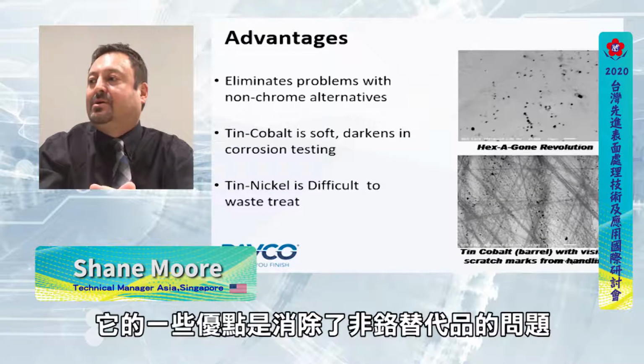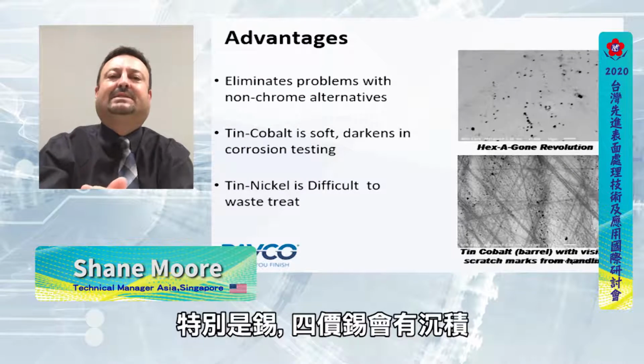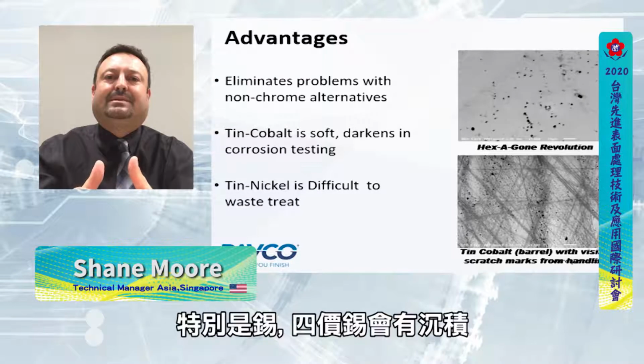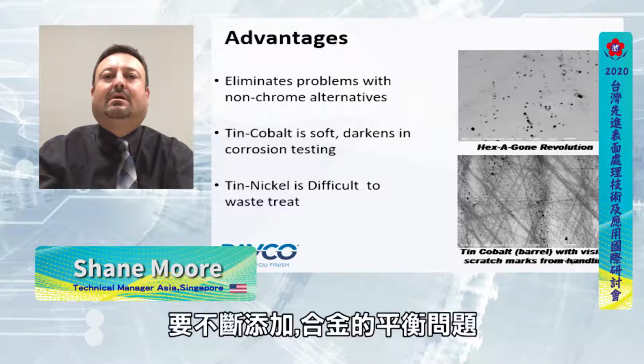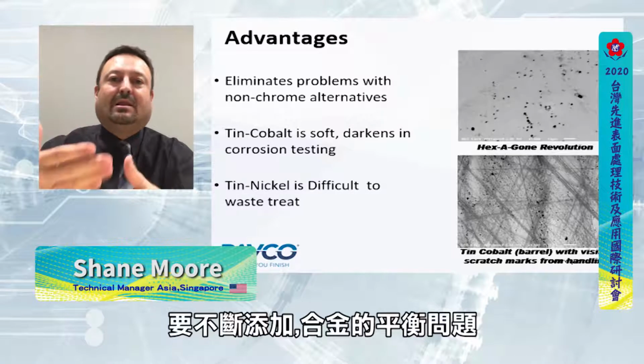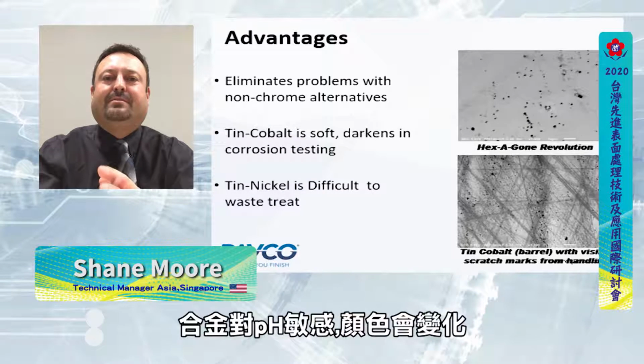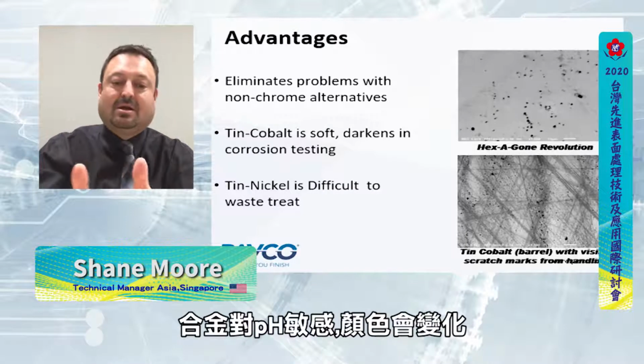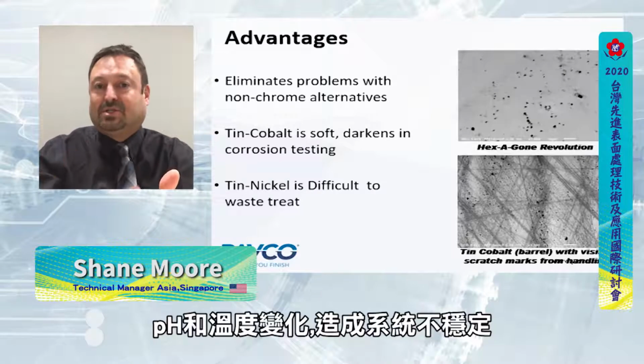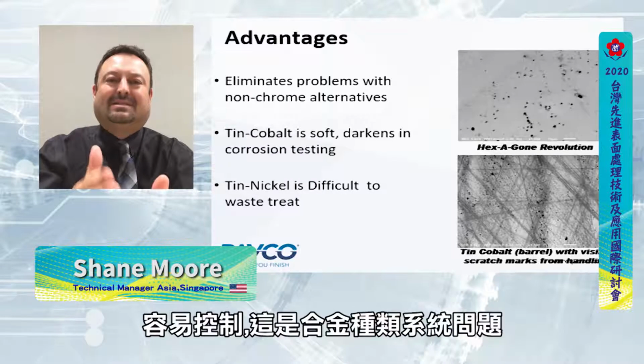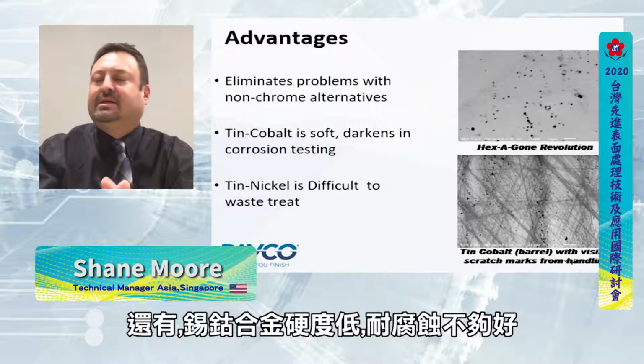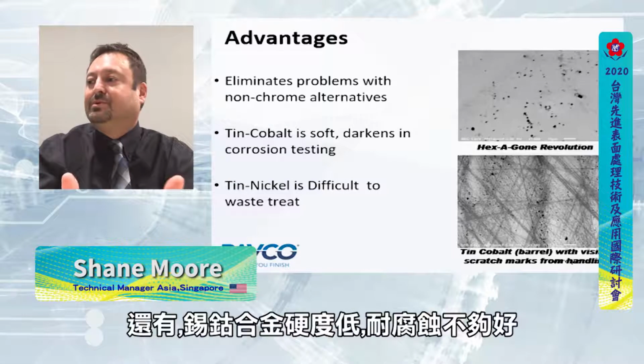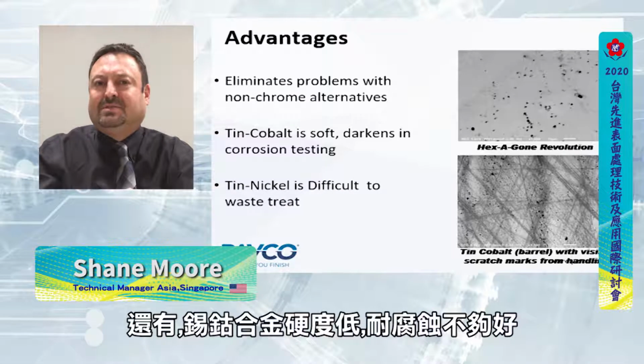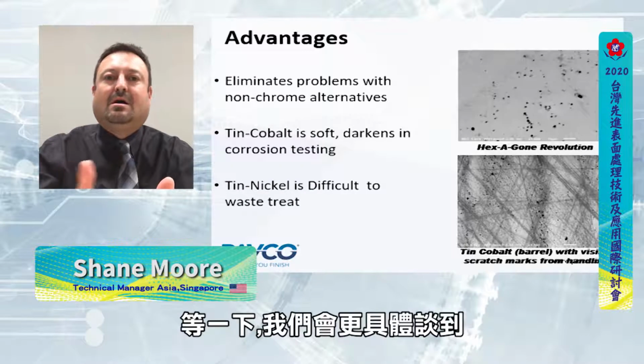Some of the advantages are, like I said, it eliminates the problems with the non-chrome alternatives, especially with tin, because tin tends to develop stannic tin. It precipitates out. You have to constantly add it back. So your alloy is out of balance. Most of the alloys are very pH sensitive, so you can actually change the color of the deposit by allowing the pH to fluctuate or the temperature to fluctuate. They're not quite as stable, and it's hard to keep it as consistent with the alloy type. Also, tin cobalt and all the tin-based ones really are very soft, not very corrosion resistant. Actually, functionally it is, but we'll see.